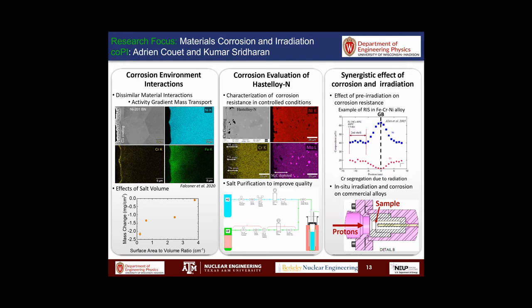Another effect that the Wisconsin team tested is the effect of salt volume in the experiment. When all experiments use the same salt at the same temperature for the same duration in the same geometrical setup, but with crucibles of different surface area and salt volume ratios, they were able to note a relationship between the amount of salt used in the experiment and the observed mass changes in the sample. Whether this is due to lower overall impurities being consumed or corrosion product saturation slowing down or stopping corrosion is still being investigated, but it's a crucial element of what we do. Eventually, our goal is to evaluate the effect that irradiation has on corrosion in a salt environment, namely whether radiation-induced segregation can be realized in alloy N.